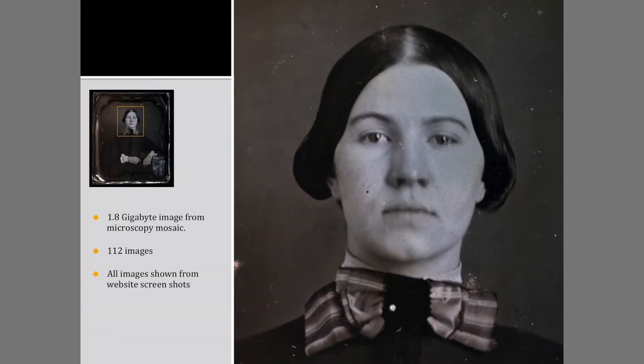We used a photo microscope, the Leica Z16 APO, with an LED ring light. We modified a macro-focusing rail to manually control a stage that supported the daguerreotype. A manual image overlap of about 20% was generally successful. We found Microsoft's Image Composite Editor, ICE, software to be the most reliable for image stitching for the final mosaic.